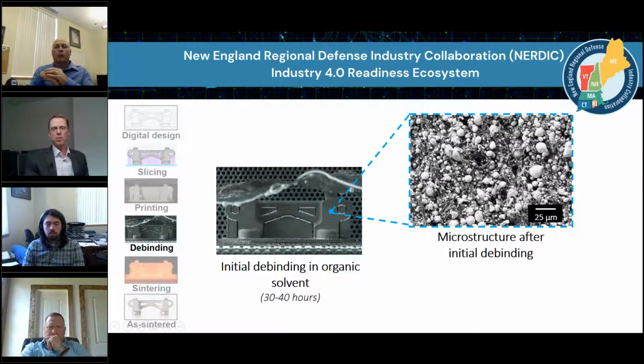One of the reasons why material extrusion is substantially less expensive than powder bed fusion is that with powder bed fusion, you have to have very consistent size particles. That's to make sure that you don't get vaporization or ablation or any other deleterious process as heat goes into each particle. But here, because the thermal gradients are low, you can use more of a developed powder stream, typically from metal injection molding.